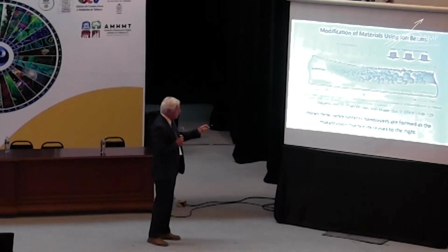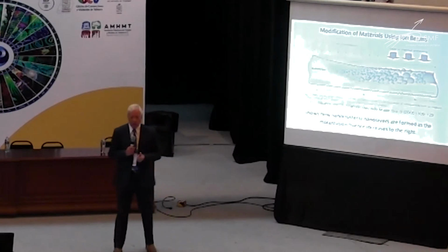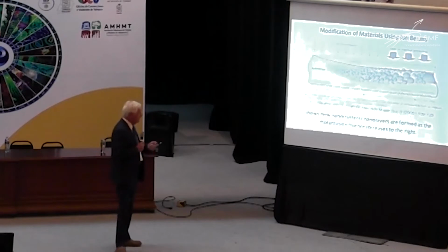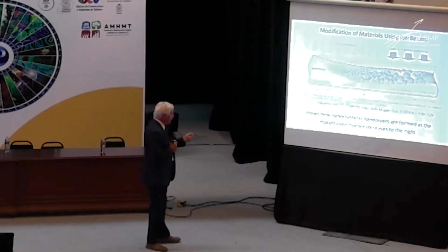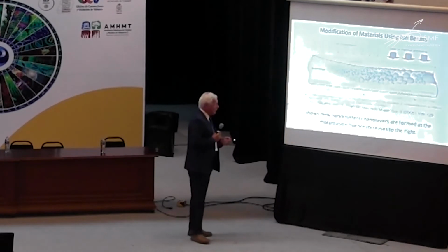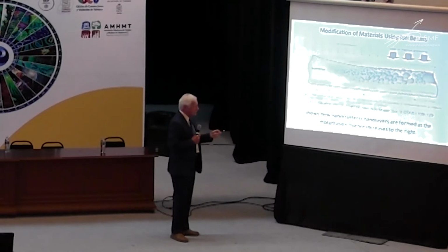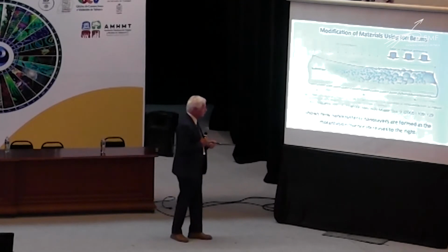you start sputtering the material away. This causes a little bit of a problem, but it also helps us in another way. You can see that what's forming here in the substrate are what we call nanoparticles. The lower the fluence, the smaller the nanoparticle. The greater the fluence, the larger the nanoparticle. The greater the fluence, the more material is sputtered away.